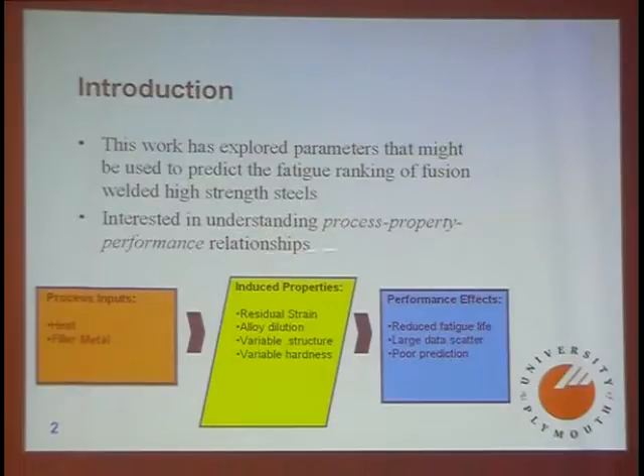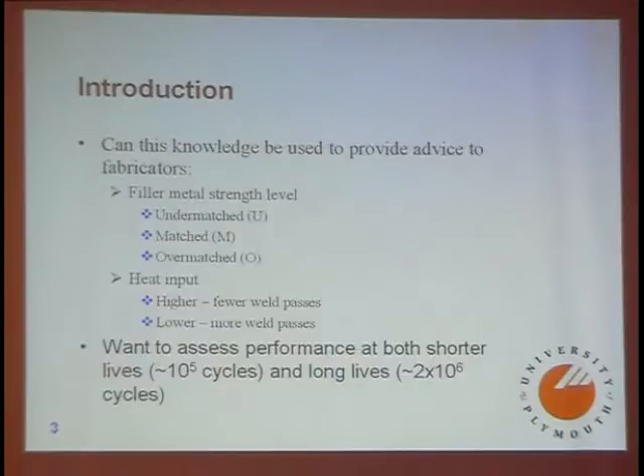And so I'm interested in understanding process-property-performance relationships. In other words, in welding, you've got process inputs: you use a filler metal, you use some heat, and you get a variety of induced properties. You have residual strain, you've got dilution of the alloy in the fusion zone, you have a variable microstructure and a variable hardness. And that makes it quite difficult to predict performance more precisely. What you tend to get is reduced fatigue life, large data scatter and poor predictive capability. So if we're going to advance that, we do have to take some account of what welding is doing to the microstructure.